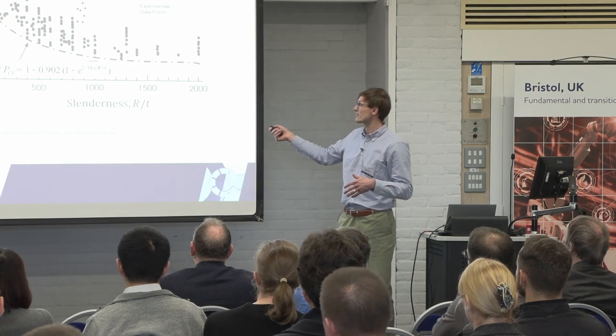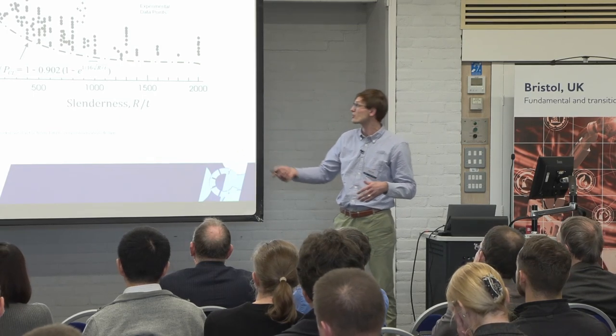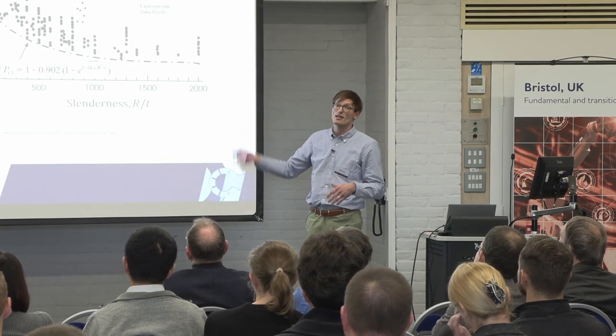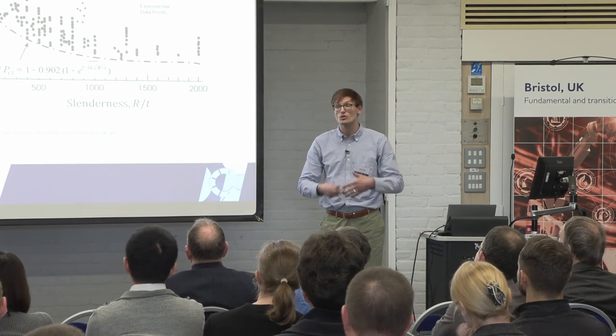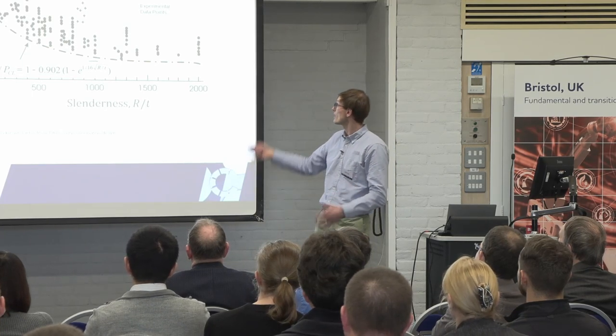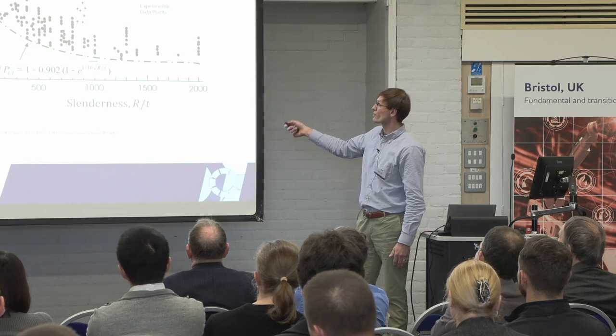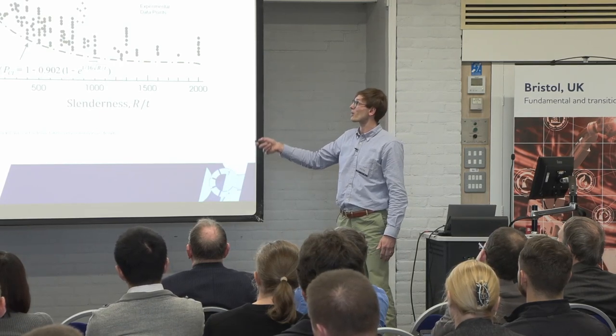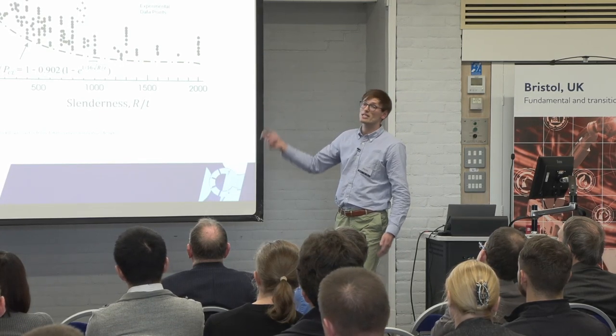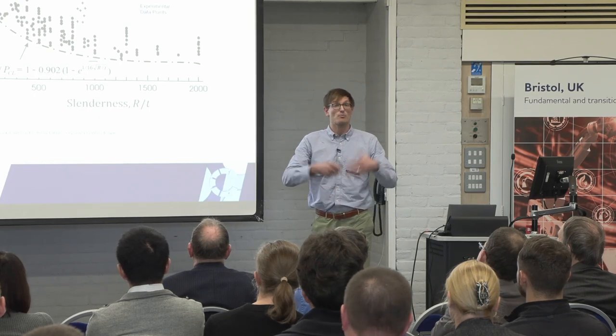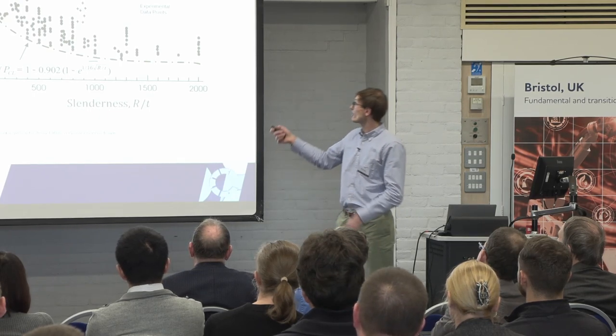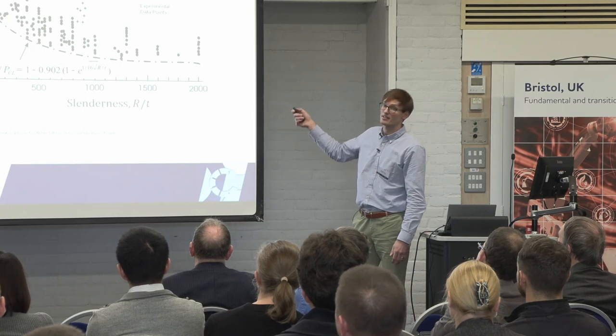And this horizontal axis here is the radius to thickness ratio. So the further we go to the right, the more slender the cylinder becomes, but also the more lightweight and efficient it becomes. If we're trying to operate in this range over here, we have this problem that we're operating at 20% of the capacity of a perfect structure. And on top of that, there's this big spread in these buckling loads.